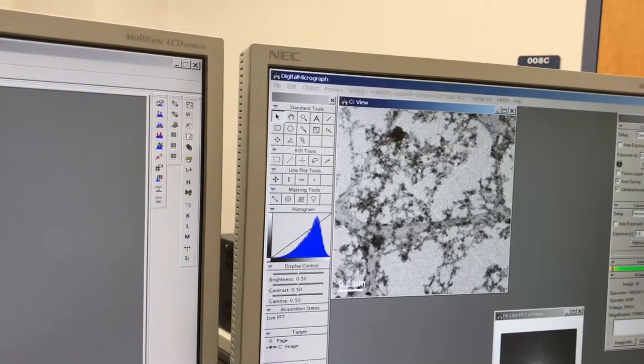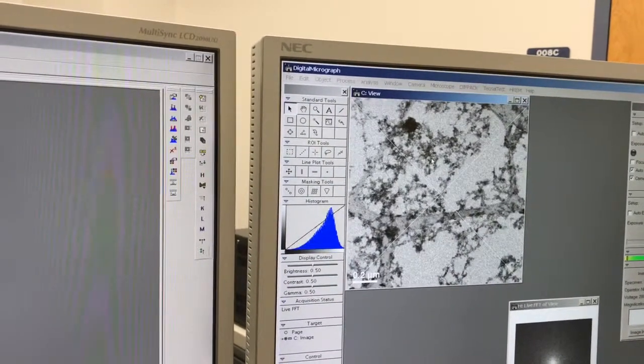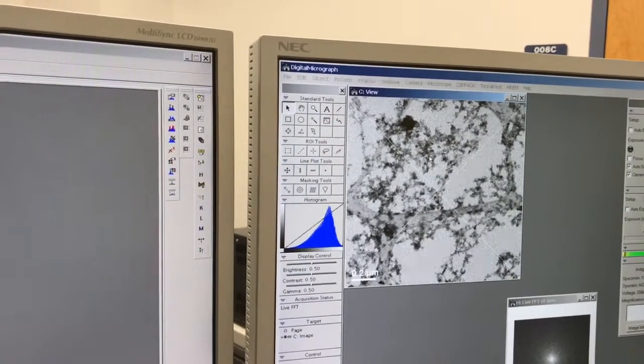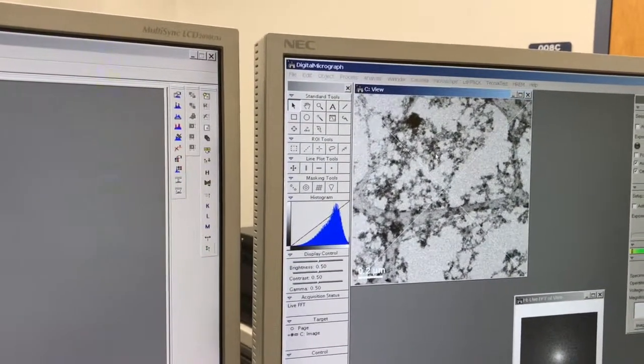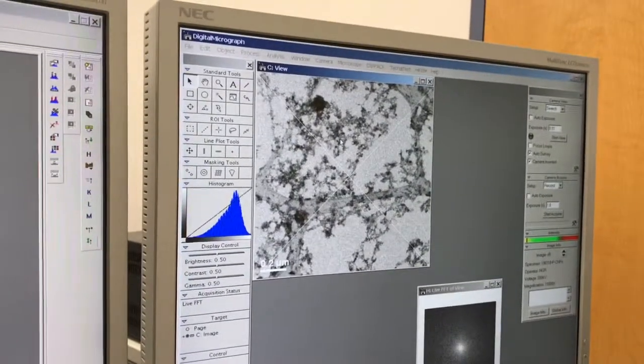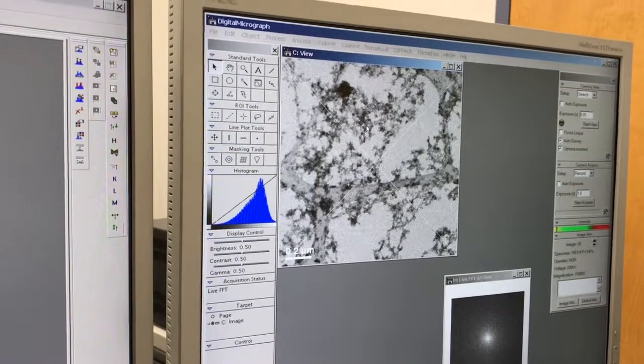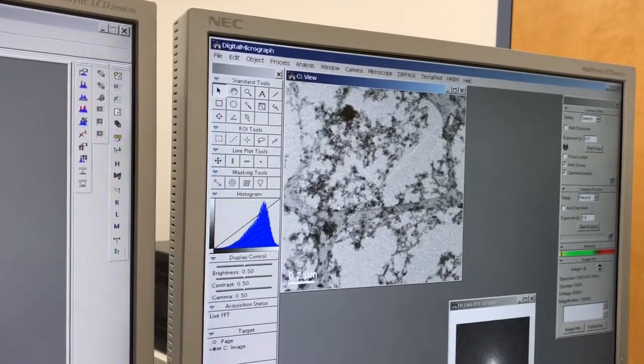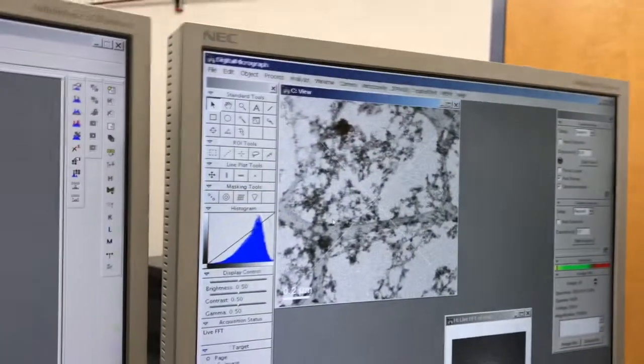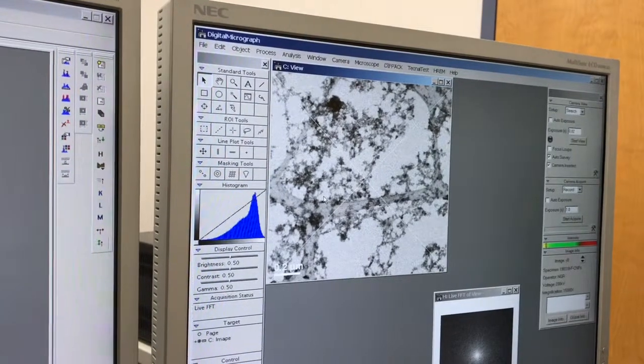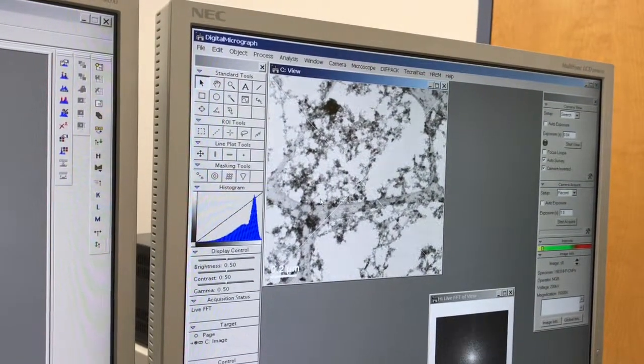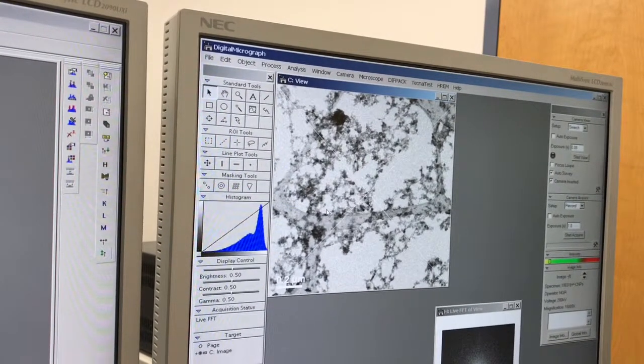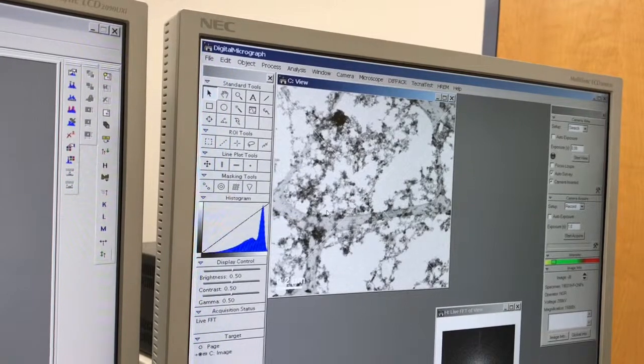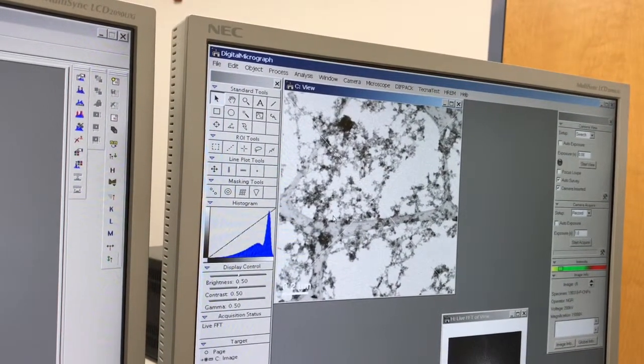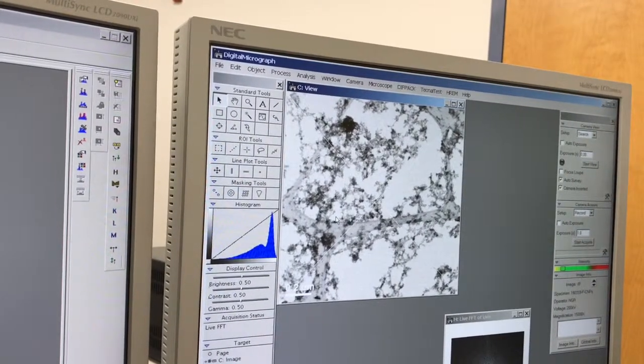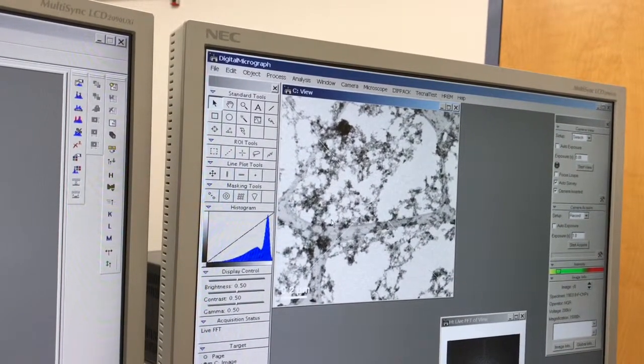Okay, and so the noise itself is not really dependent on the exposure time, but the signal, the good part of the image, is. So if I increase the exposure time, my signal to noise ratio improves and I get a better quality image. If I click on view here, and this is a shortcut, I hit up arrow, it doubles it, you can see what's happening here. I'm at 0.04, now I'm at 0.08. The image quality improves dramatically as a result of doing that, because my signal to noise ratio goes up as I increase the exposure time.